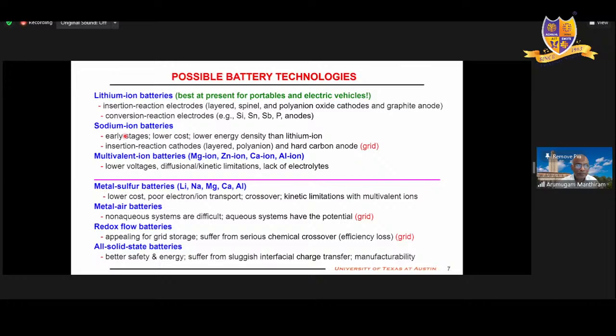Finally, sodium sulfur is my dream technology. Electrolyte is the major problem. Conventional electrolytes lead to a lot of gassing and safety problems and dendrites. We have used a localized high concentration electrolyte. That kind of gassing and dendrite is suppressed. And then the dynamics also change. Usually with sulfur, as I mentioned earlier, it is a dissolution-precipitation reaction: it dissolves, solidifies. We change that to a quasi-solid state reaction, and that gives you this kind of performance. This is the best data available in the literature as far as sodium sulfur is concerned.